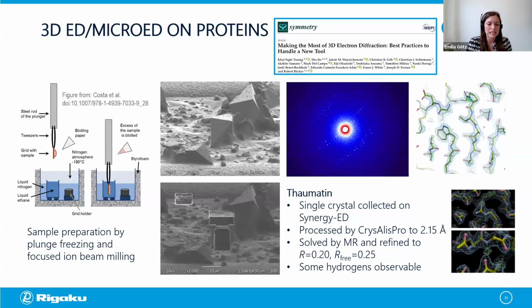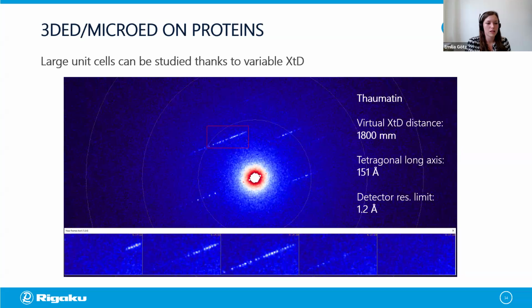Of course, the sample preparation is a lot more complicated and time-consuming than for non-protein samples, although there are several methods to be considered and some might require less effort than others. But in this case, we managed to process the collected data to 2.15 angstrom and solve and refine the structure with even some hydrogen atoms observable. These long axes of proteins, or in this case, thaumatin, can be measured on the Synergy-ED because we can go to some pretty long detector distances. In this case, the data was collected at a detector distance of 1.8 meters, while still having a 1.2 angstrom resolution on the detector. But in theory, we could go up to even 3 meters. So there is some space to resolve some even longer axes.